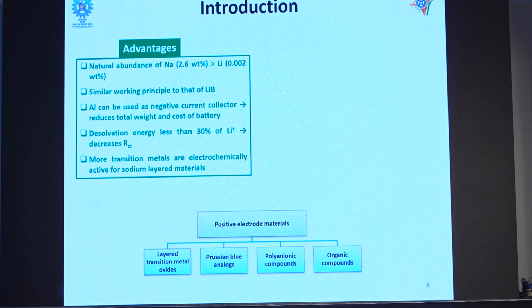Normal lithium-ion batteries use aluminum as a current collector on the cathode side, and copper as a current collector on the anode side. Copper is very expensive generally. So if you can replace copper with any other metal... In lithium-ion batteries, why we use copper is because the voltage of the negative electrode is not compatible with aluminum, and the lithium will form alloys with aluminum. But in a sodium-ion battery, we don't have sodium-aluminum alloy formation. So we can use aluminum on both sides, cathode side and anode side. That makes it more cost-effective.